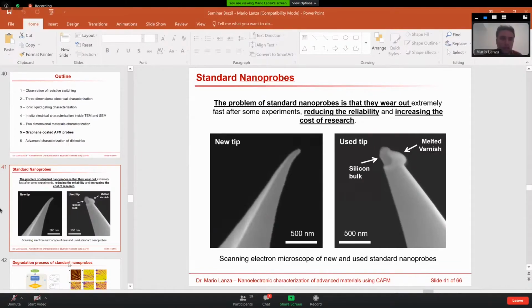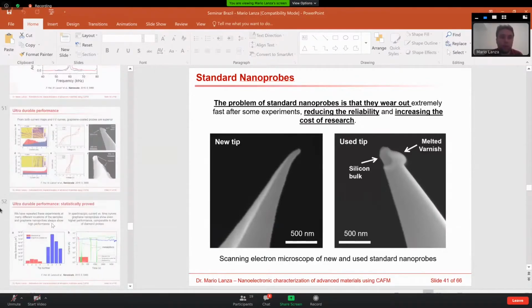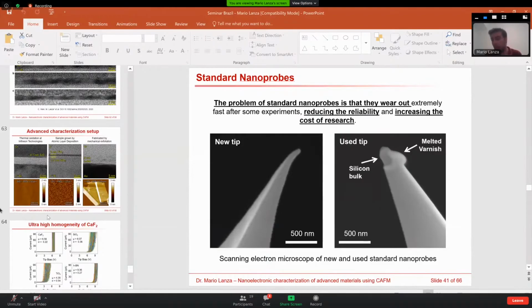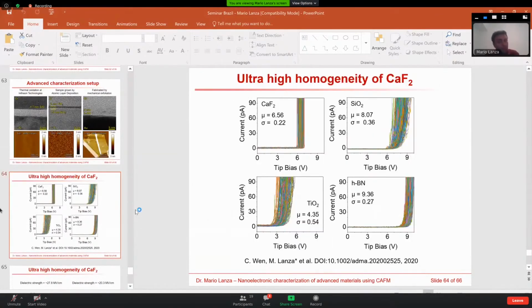That is a very, very good question. One of the main theoretical studies that we do is, when we measure the IV curves at different locations of the material, we can also do fittings. We can fit these IV curves, which are measuring the leakage current, to different conduction mechanisms, like direct tunneling, Fowler-Nordheim tunneling, trap-assisted tunneling, Poole-Frenkel emission. This fitting can help us understand the way in which the electrons are flowing across this dielectric. That is the main study that we do.